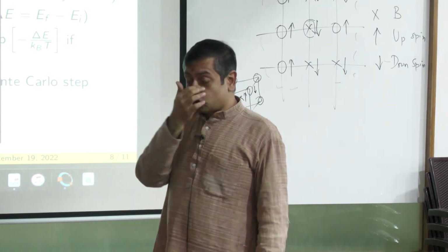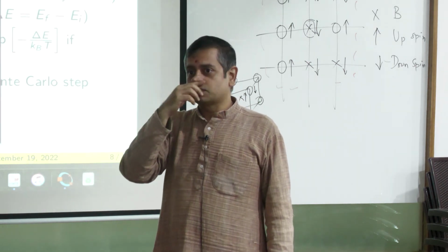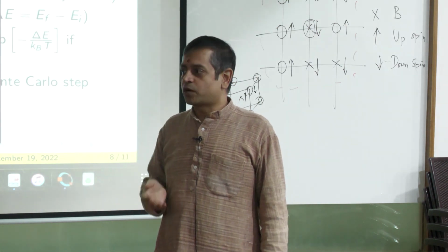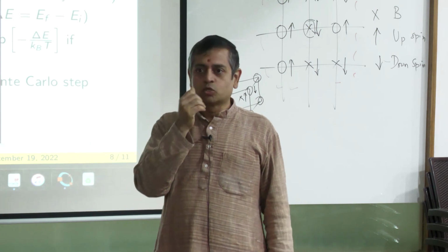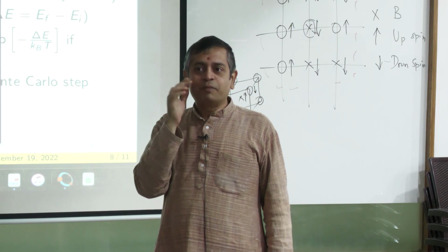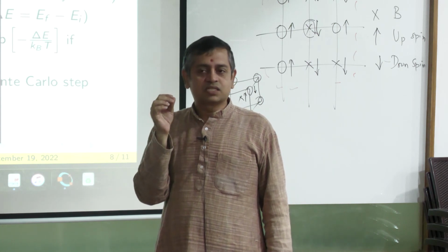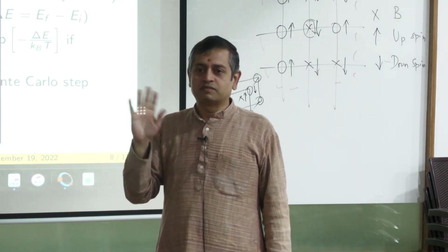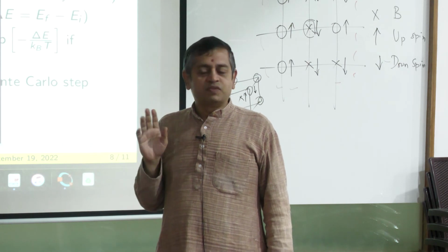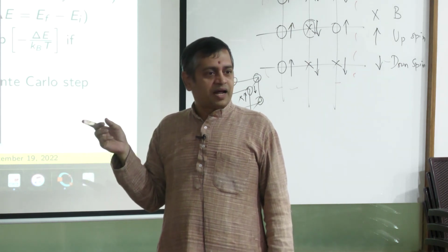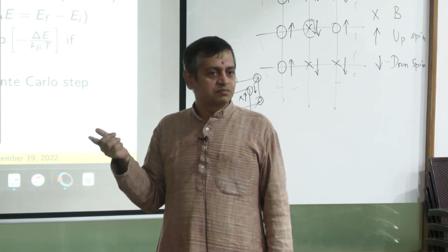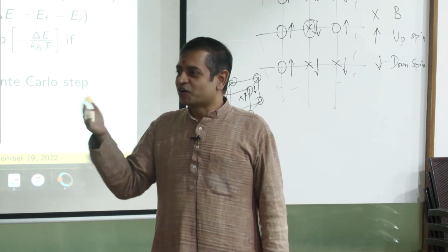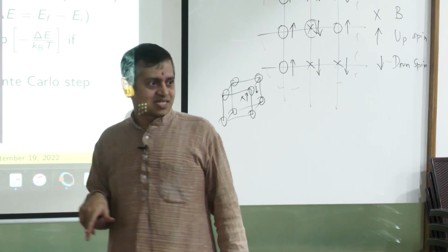Okay. In this lattice there are no vacant sites. Sometimes you also do simulations by introducing one vacancy. There again the system size becomes important, as you would know or most probably would know. At melting point, most of the materials will have vacancy concentration of the order of 1 in 10,000 atoms. 10 power minus 4, 10 power minus 5 is typically the vacancy concentration. So, which means if you are doing a Monte Carlo simulation, unless you have 10 power 5 atoms, you cannot introduce one vacancy if you are doing the simulation at melting temperature. Okay. Come to lower temperatures, it is still smaller concentration.